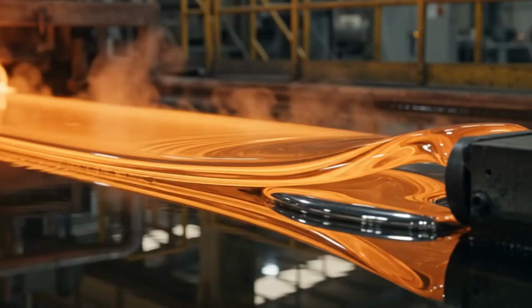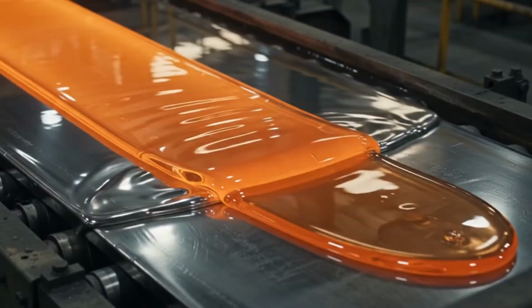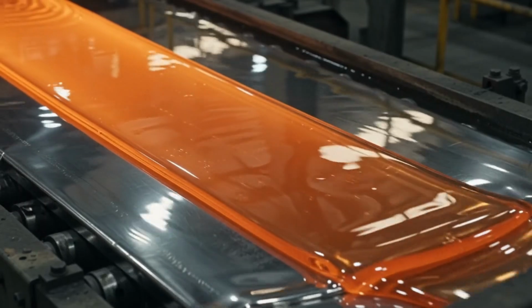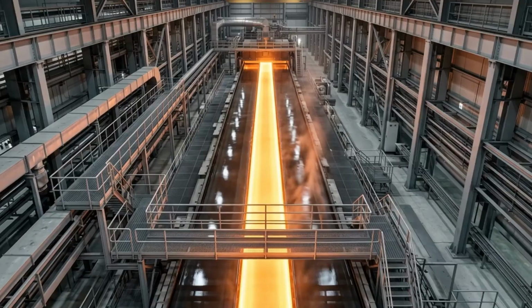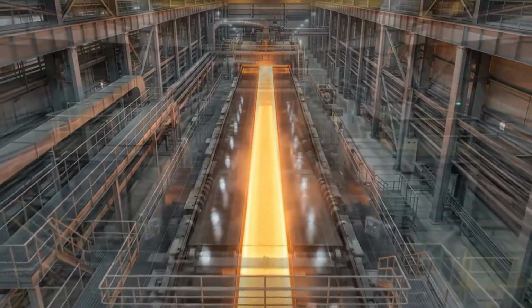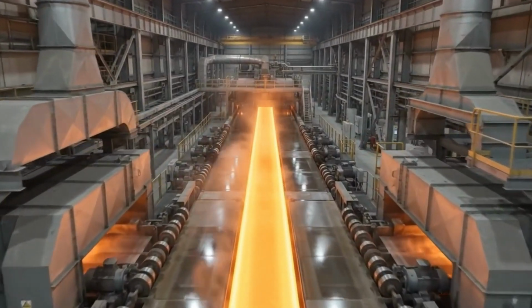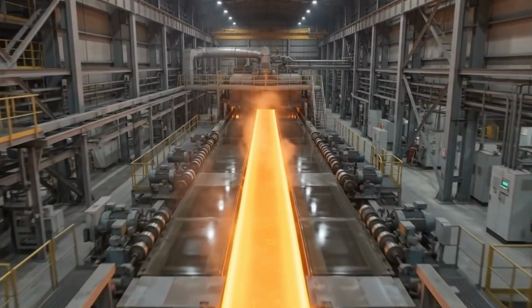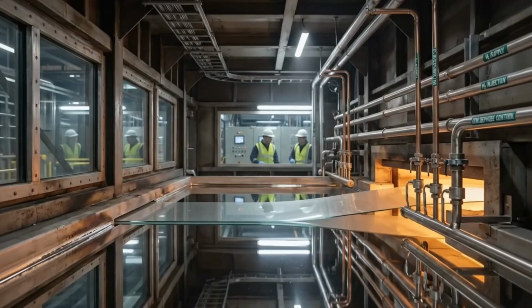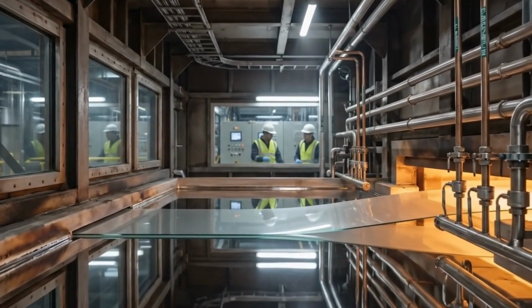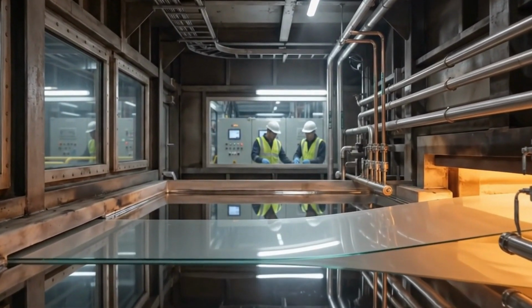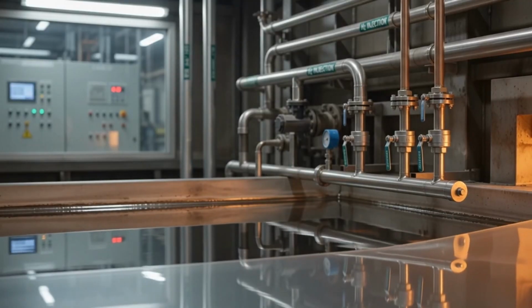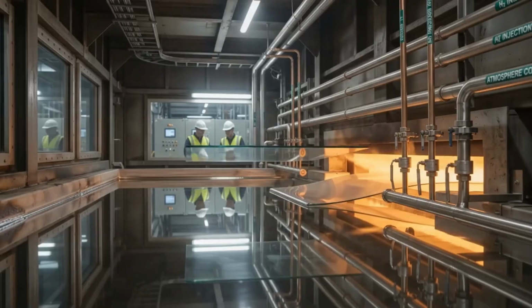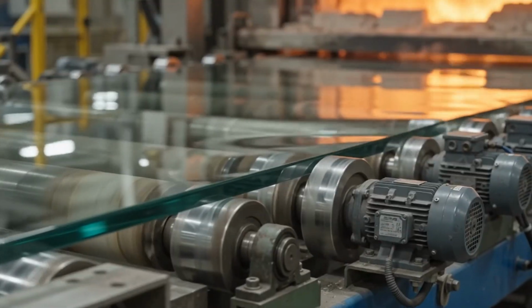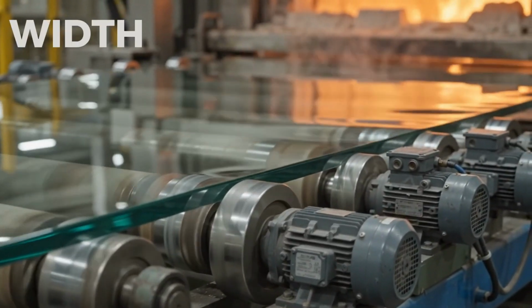The glowing ribbon stretches across the tin bath like a river of light. But despite its smooth appearance, it's still more than 1,800 degrees Fahrenheit. Cooling it too quickly would create invisible stresses trapped inside the glass. Cooling it unevenly would cause distortions. Even the atmosphere above the molten tin must be carefully controlled. Oxygen is kept away to prevent the tin from oxidizing and damaging the flawless surface below. Meanwhile, rollers along the edges gently control the ribbon's width and thickness.